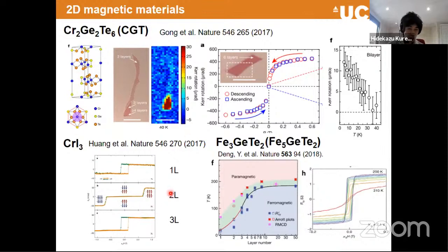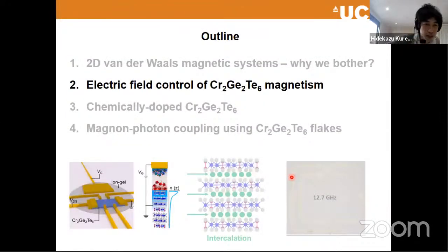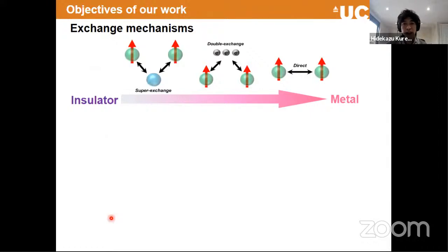While these two are insulators, we also have some itinerant metallic systems, which are iron-based systems. So we have a variety of 2D magnetic systems, so that we can pick the one that we want to work on, either the insulating regime or the metallic regime for applications. Then I will dive into a particular project that we did in the last few years. The first one is the electric field control of chromium germanium telluride. We make a FET device and put an ionic gel on top of it for gating, and then try to see how the magnetism can be different depending on the carrier doping.